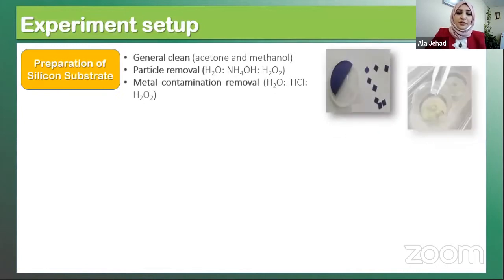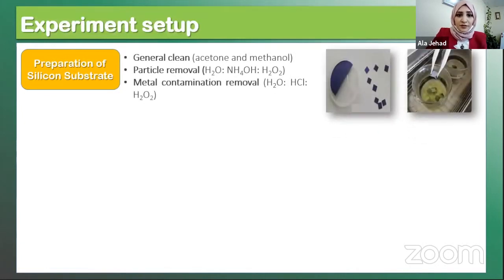The experiment work first was the preparation of the silicon substrate. As you can see in the image, we first cleave the silicon wafer to an area of 1 by 1 centimeter. Then it moves to the cleaning step, for which we used 3 different steps. First one was general clean, where we used hot acetone and methanol, and then particle removal, where we used the standard RCA method to clean the wafers, and then metal contamination removal, where we used hydrochloric acid and hydrogen peroxide. After each step, the silicon substrates were washed with a rinse of deionized water and dried with nitrogen gas.